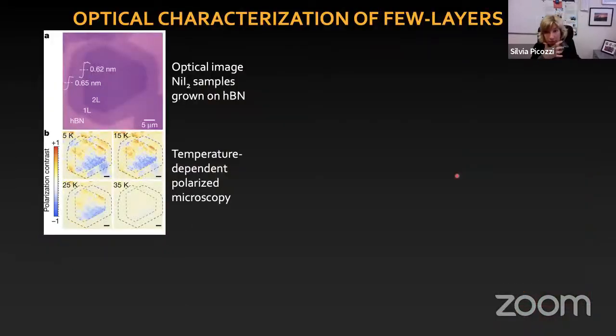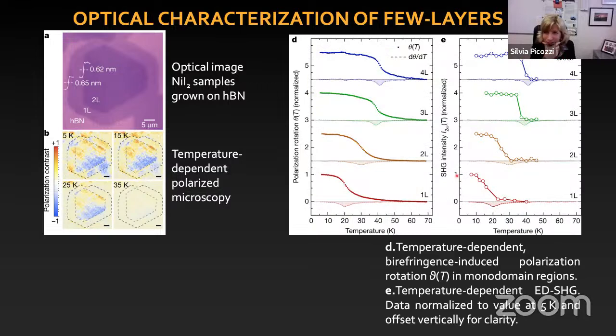And so what Riccardo and colleagues did was they took the crystal and then they exfoliated the layers. And they did also a few layers, 4 and 3 and 2 and 1 layer. And then they did nonlinear optics. So they did second harmonic generation and linear dichroism. And they measured this 1 layer, 2 layer, 3 layer, 4 layer. And so what you see here is that you have a signal which pops up below, I don't know, 40 Kelvin. What seems to be an ordering temperature is actually decreasing if I reduce the number of layers. But even for a monolayer, I have a clear signal.